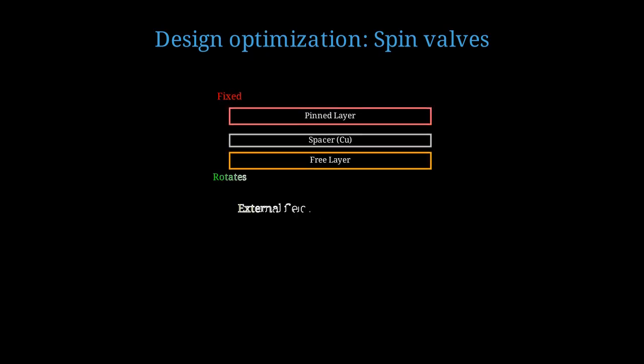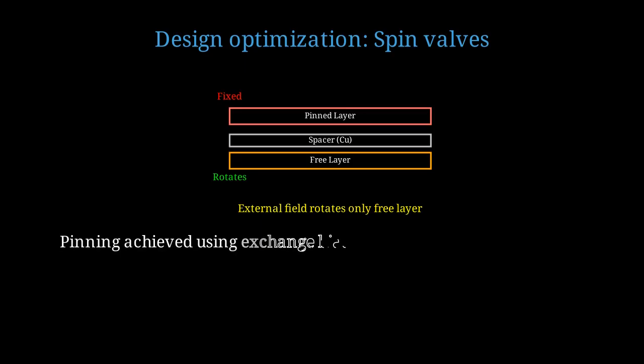A spin valve consists of a pinned magnetic layer whose magnetization is fixed in one direction, a thin copper spacer, and a free layer whose magnetization can rotate in response to small external fields. Only the free layer responds to the weak stray fields from disk bits, while the pinned layer provides a reference direction. The pinning is achieved by depositing an antiferromagnetic layer adjacent to the pinned layer. This creates exchange bias, a strong interfacial coupling that requires large fields to overcome, typically hundreds of Oersteds.